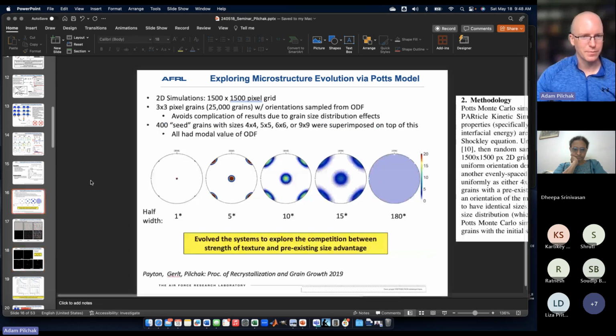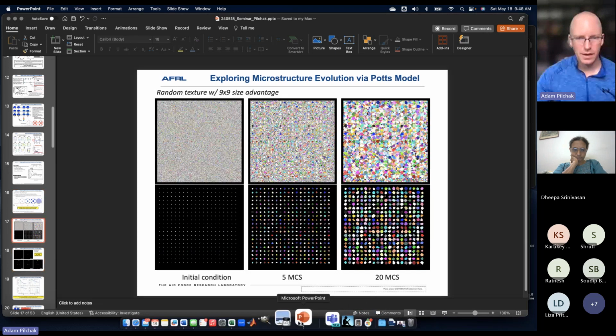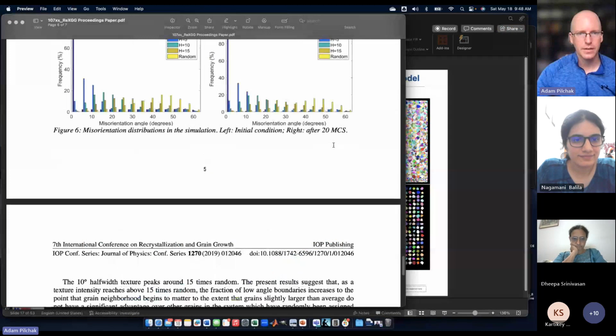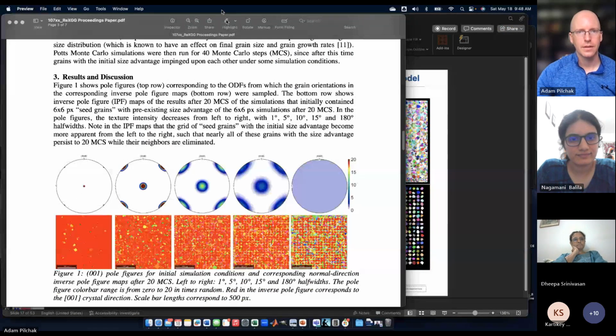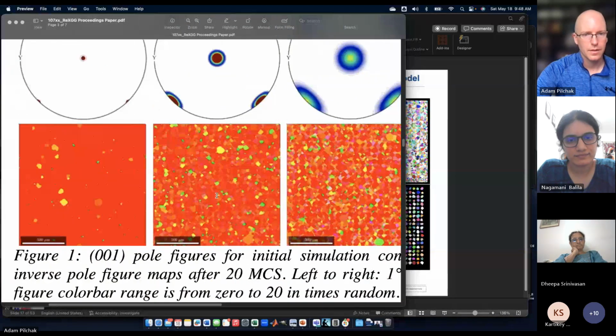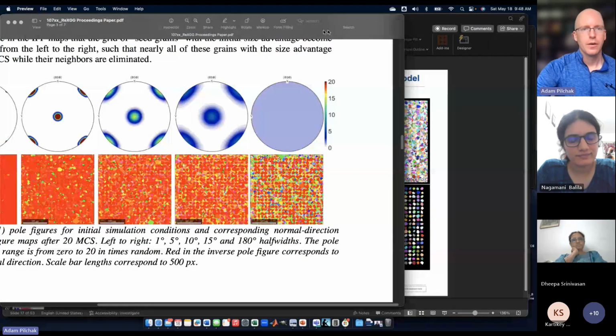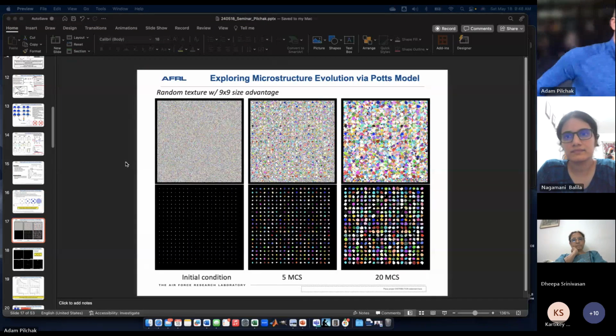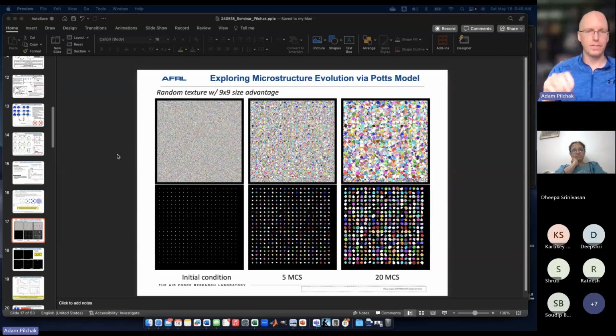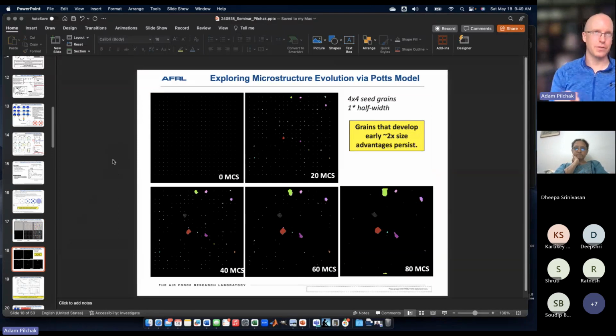And I really wish I had a graphic to show this better, but I do not have it at my fingertips. Let me see if the paper has anything better in it. Yeah, that's not going to help either. But remember that the seed grains were all the average orientation. The subgrains in the background were all sampled from those different ODFs. And so it's possible that two of the matrix subgrains had some high misorientation, making those boundaries pretty mobile themselves. So it's just a competition between the grain boundary energy and mobility of the seed grain versus its nearest neighbors.